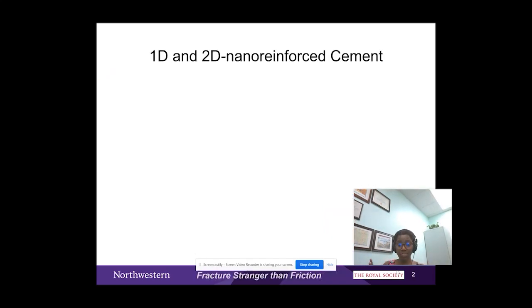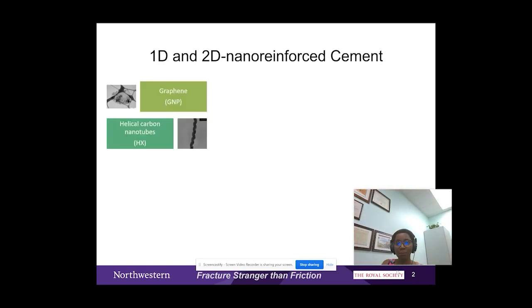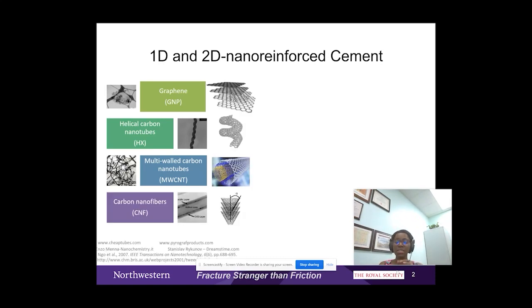There's a wide range of nanomaterials, and today I'm going to be focusing on 4 types of carbon-based nanomaterials: graphene nanoplatelets, helical carbon nanotubes, multi-wall carbon nanotubes, and carbon nanofibers. In terms of dimension, the thickness of the graphene nanoplatelets is 8 to 15 nanometers. The diameter of the helical carbon nanotubes and multi-wall carbon nanotubes is 20 to 50 nanometers. The diameter of the carbon nanofibers is 150 nanometers. In terms of length, the dimension of the graphene nanoplatelets is 1 to 2 microns. The length of the multi-wall carbon nanotubes and helical carbon nanotubes is around 50 micrometers, and the length of the carbon nanofibers is between 50 to 200 micrometers.